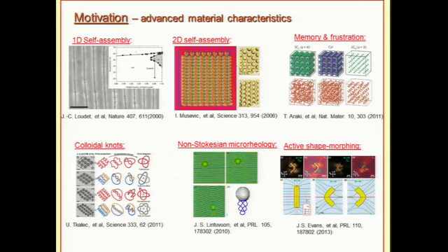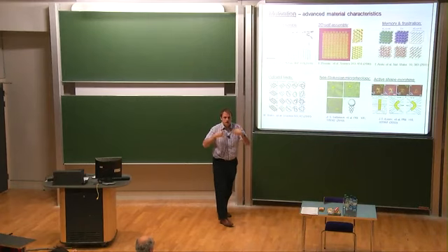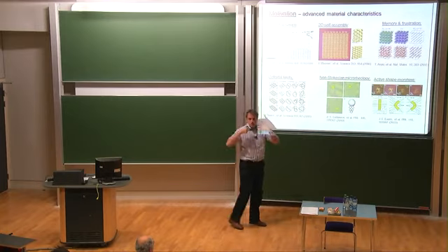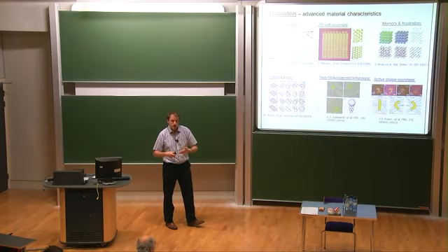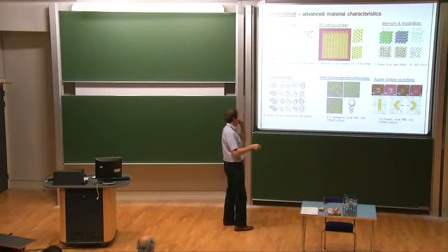And what's special about them, when they put liquid crystals, the nematic liquid crystal in, they see a complex conformation of defects, okay? I hope you see it. So just this complex lattice of defects. And now what they do next, they apply external fields. And when they apply an external field, they imprint into the material a very distinct structure, and even when they remove the field, this structure remains there. Okay, so this is a clear signature of memory. So actually, by imprinting conformations of defects into this, you can create memory states. Okay, this is one interesting example from the literature from the past years.